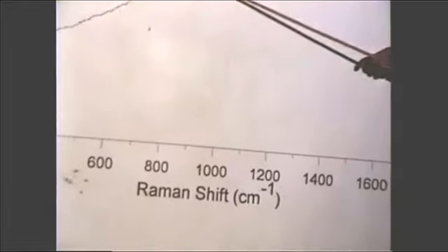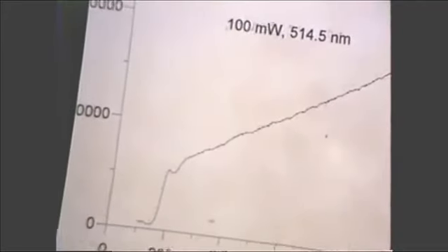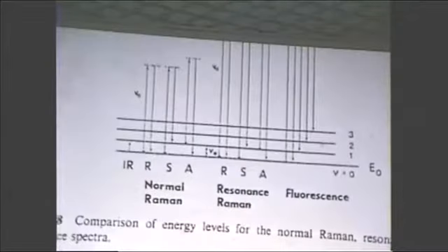And all you see in the spectrum is just a broad background of fluorescence. And you see essentially no indication at all of any nice sharp peaks that you would expect for a vibrational transition in the catalyst. The problem here is that the typical molecules produced in a hydrocarbon reaction that form coke cause this fluorescence, so that virtually any catalytic reaction involving hydrocarbons is a problem to study with Raman spectroscopy. The only exception to that are oxidation reactions, where you have oxygen to burn the coke off the